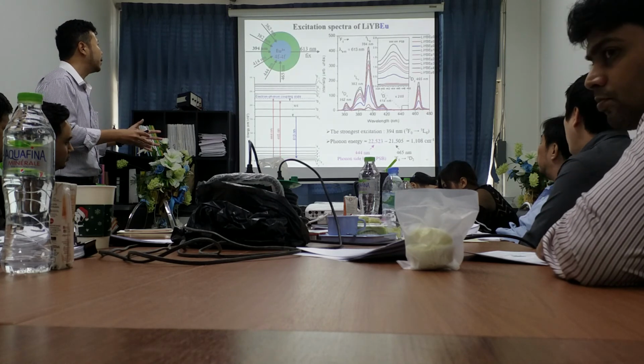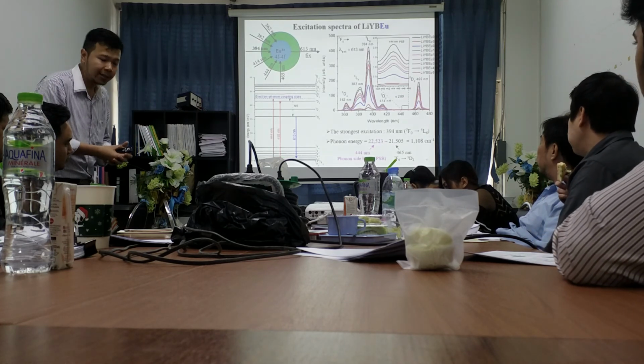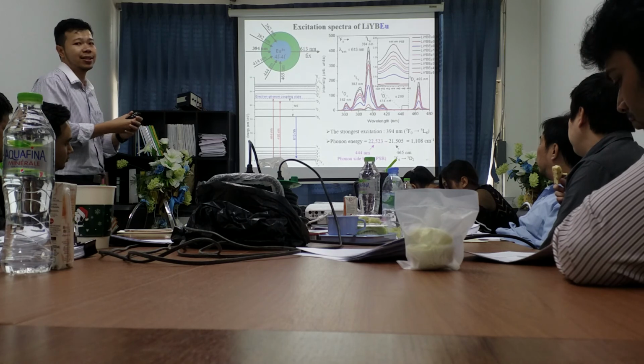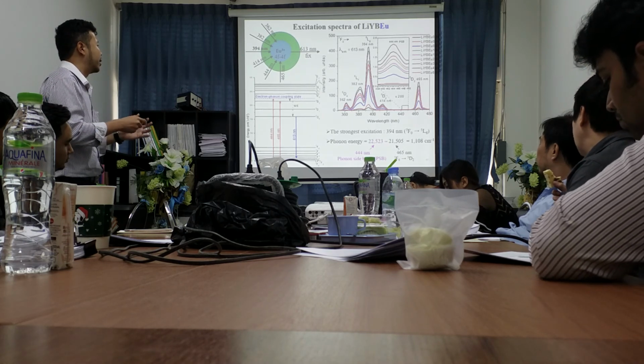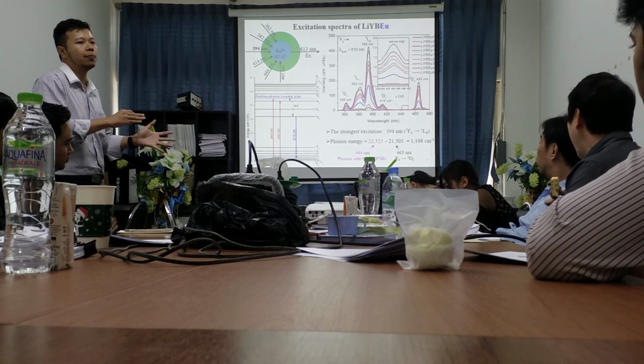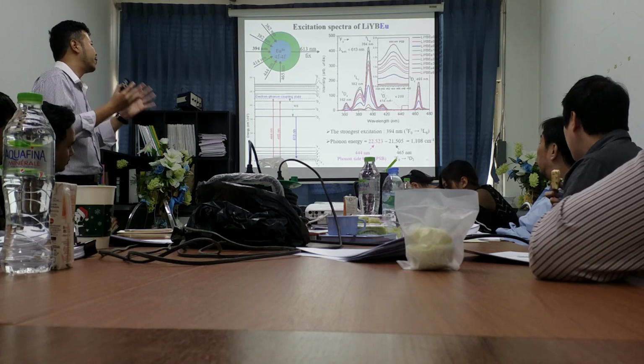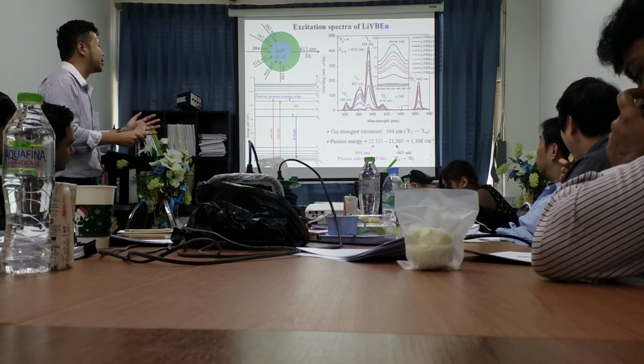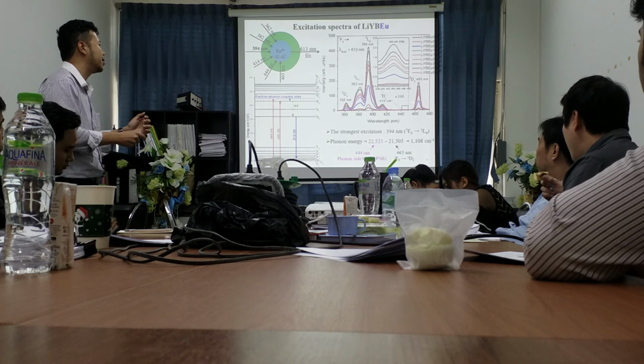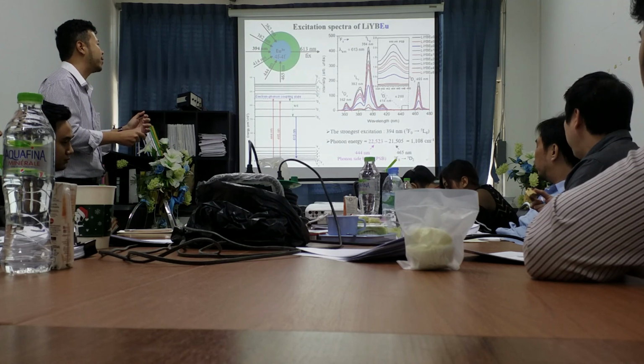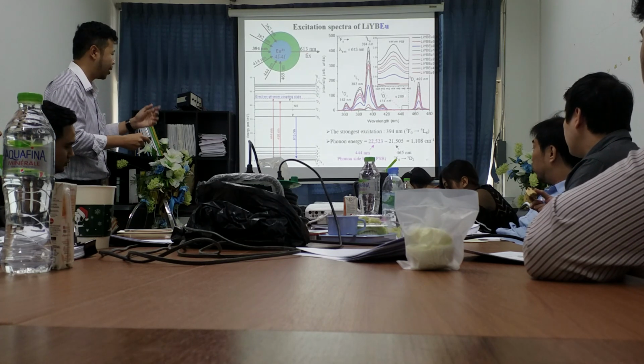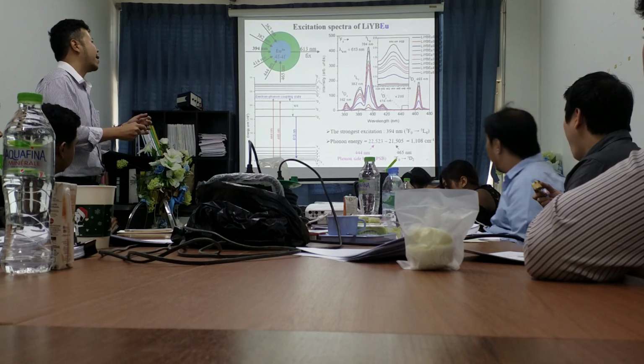To confirm the excitation wavelength, I measured the excitation spectra. It corresponds with the emission spectra, but however, we found a small phonon sideband here. This is the amplification about times 200. This phonon sideband occurs